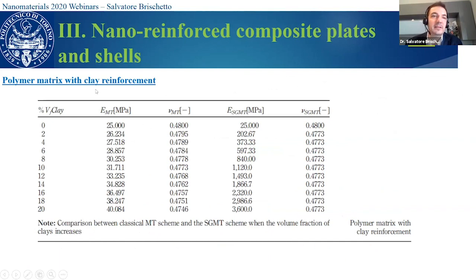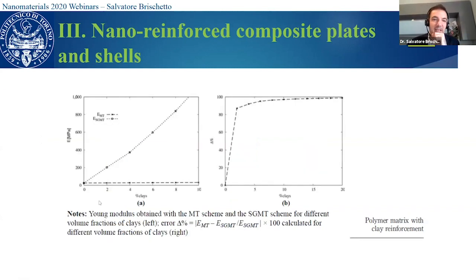Obviously, another last possibility is the use of clay reinforcement in polymeric matrix. In this case, in order to calculate the equivalent Young modulus, we can use the Mori-Tanaka scheme or the strain gradient Mori-Tanaka scheme. And it is important to use the strain gradient Mori-Tanaka scheme because when we have very small reinforcement, we have some strain gradient at the interfaces between the matrix and the reinforcement, and we must consider this effect in order to obtain the correct values. So we can see the difference when the percentage of clays increases. This is the Young modulus obtained by means of Mori-Tanaka scheme, and this is obtained by means of strain gradient Mori-Tanaka scheme. Okay.